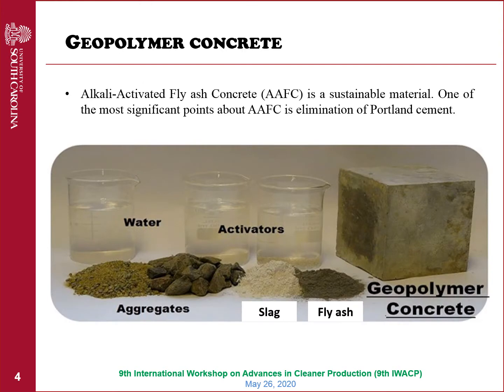So the geopolymer concrete, or sustainable concrete, that we are using consists of an activating solution such as sodium silicate, sodium hydroxide, or a mixture of silica fume and sodium hydroxide, and a source of aluminum silicate such as fly ash, and fine and coarse aggregate.